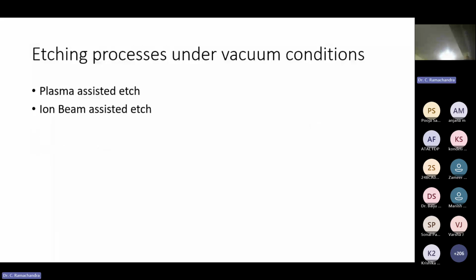Now, when you come to the vacuum conditions, under vacuum condition, what are all the steps we can do? Broadly speaking, there are two techniques. One is called plasma assisted etch. Another is called ion beam assisted etch. In plasma assisted etch, the vacuum level is relatively low. But when you go to the ion beam assisted etch, it is very high vacuum. Plasma assisted etch has very high throughput. Therefore, it is used in manufacturing production. Whereas ion beam assisted etch throughput is very low. It is used for some device modification or some trial run, some experiment. It is not for manufacturing throughput. We'll cover how plasma assisted etch works and how ion beam assisted etch is useful.